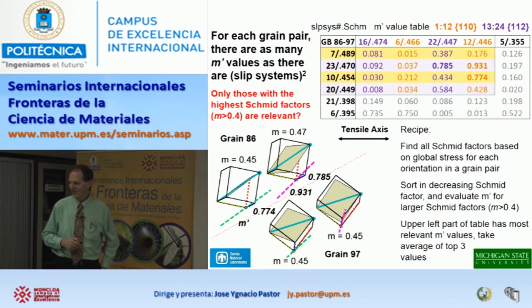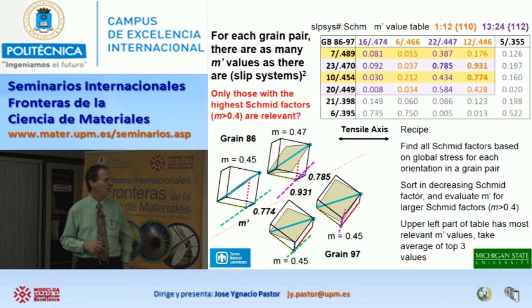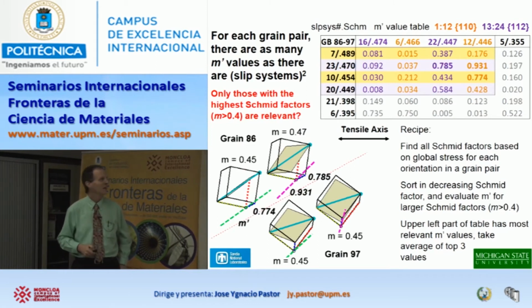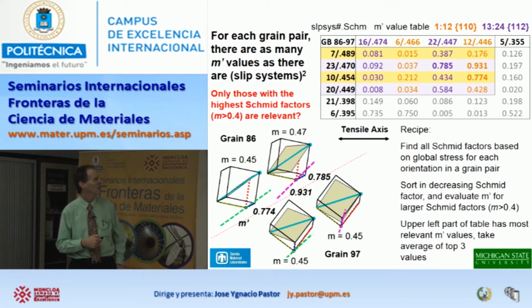So I'm going to give you an example of how this analysis might go. It's pretty messy, because for each pair of grains, there are as many of these M prime values as there are slip systems squared. So obviously, this only matters for slip systems in which slip is happening, because for slip systems that are not active, I don't care whether they're well aligned or not. Only the ones in which slip is active matter.